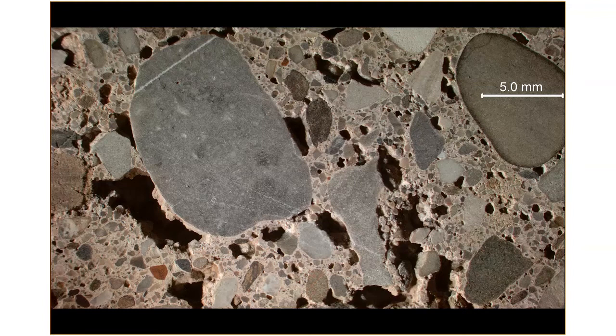And what this does not look unlike is pervious concrete pavement. Pervious concrete pavement has upwards of 15 or 20 or 25% void space. And one of the true measures of a pervious pavement is having open base, and you can pour a 5-gallon pail of water down on this concrete and it drains to the grade. And there have been lots of experiments with pervious concrete pavement.